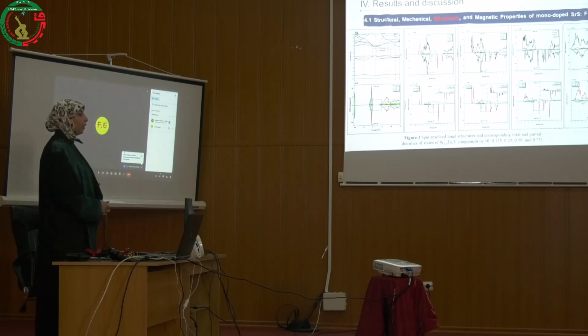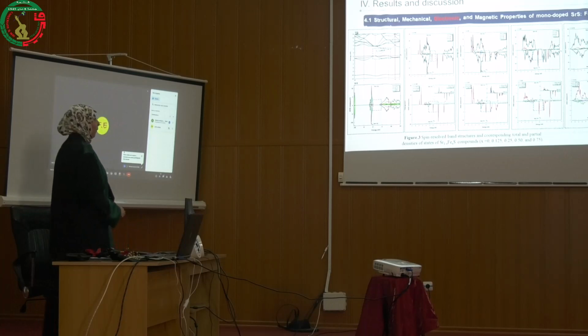This behavior is also confirmed by their total and partial densities of states, in which no states intersect the Fermi level in the majority spin, whereas the 3d eg states intersect the Fermi level in the minority spin, leaving the half metallic ferromagnetic character with 100% spin polarization. This character is also the result of the p-d hybridization between p states of the anions and d states of the iron dopant.